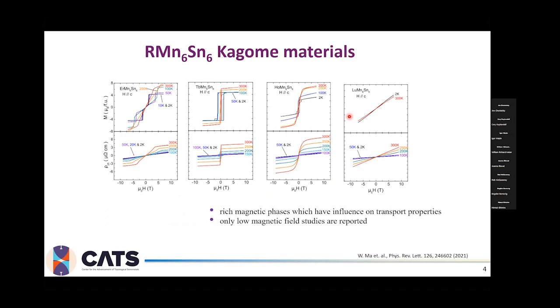So the interesting point in this paper, which was also mentioned in the first talk today, is that the magnetic properties of each of these materials very strongly influence the transport properties. And that's what we can see in the erbium compound, for example, which is an antiferromagnetic material. Then when we move to terbium, which is a ferromagnetic material, it shows a very large hysteresis, which also influences the Hall effect result.